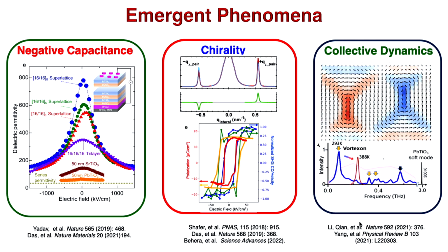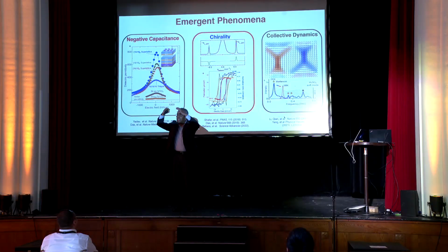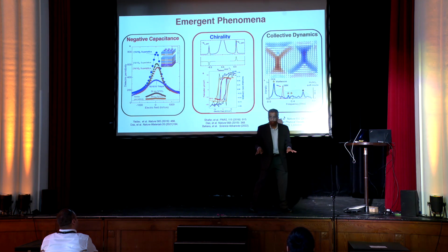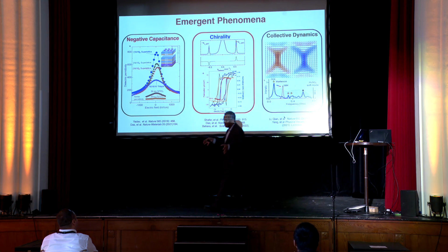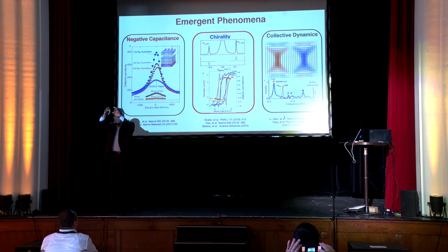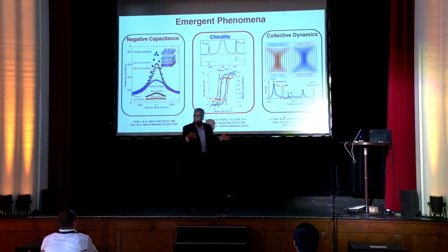So if you have layers of lead titanate and strontium titanate in series, you expect that the effective permittivity should be here, this black line. No, it's actually 20 times larger. That happens because in these systems, the vortex core is actually sitting at the peak of the double well structure, not at the valley of the double well structure. And therefore, in local regions, there's nothing that says that you cannot trap in regions of negative permittivity. Permittivity being negative, meaning the curvature, or the second derivative of the free energy, is negative.